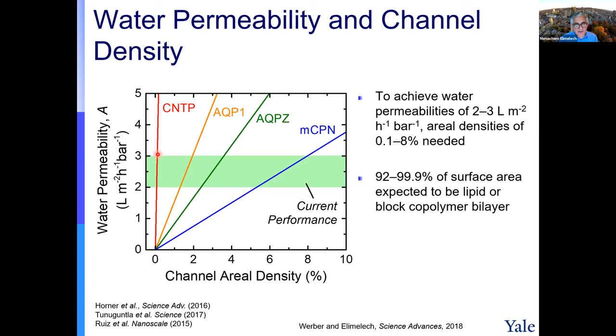For carbon nanotubes, because they're very permeable, we need less than 1% of the area covered, which means 99% of the area will be just this block copolymer bilayer. Synthetic channels are less permeable, but here we need 8%, which still means that 92% of the area will be the lipid bilayer or the block copolymer bilayer. So we see that most of the area will not be the aquaporin or the synthetic channels, but rather the other matrix. So we need now to say, okay, what will be the performance of such membranes? Because if most of the area is this block copolymer bilayer, it may control the performance of this membrane.